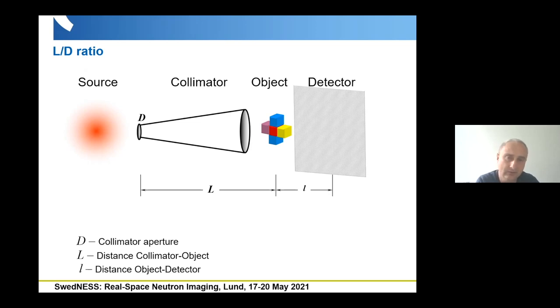So in this case, in order to obtain a really sharp image or an image with good resolution, we need to use some collimator geometry or just point source geometry, where through the collimator we can reduce the size of the source, and using a large distance we can reduce the geometrical blurring on our detector. So you can see here that this geometrical blurring, which we obtain on the detector plane, depends on the distance between the object and the detector, and also on the collimator properties, which are defined by the distance L from the pinhole to the sample, and also the diameter D of the pinhole. So this is the pinhole geometry which is described here.